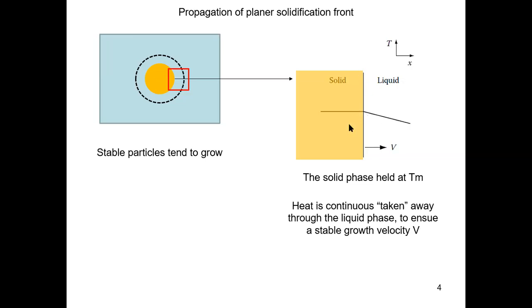But if you move away from this solidification front deeper into the liquid, we get a decrease of the temperature, because far away from the solidification front, you induce a very high supercooling. So assuming that we have just a linear decay of temperature, this is the temperature profile you see in the liquid. Okay, does this make sense to everyone?